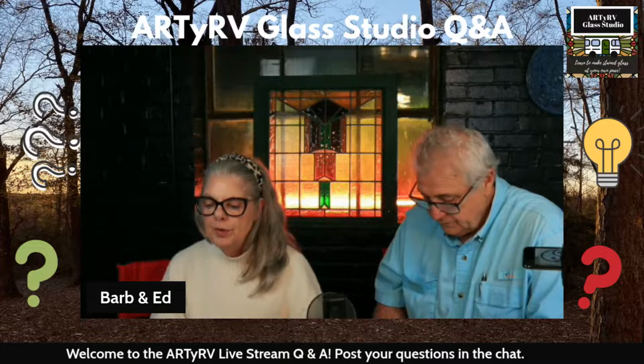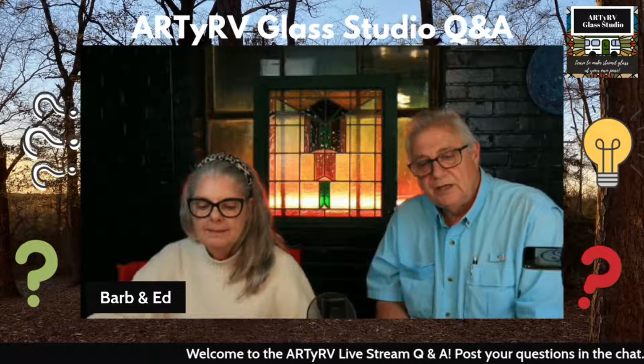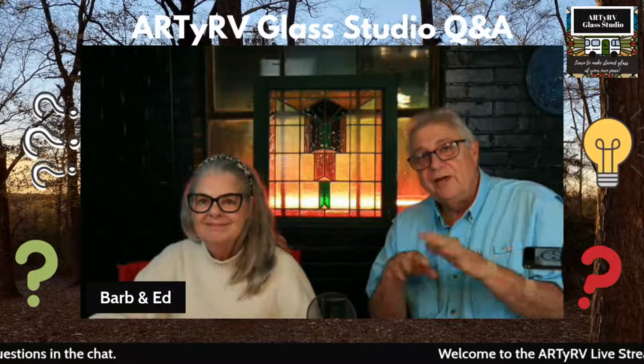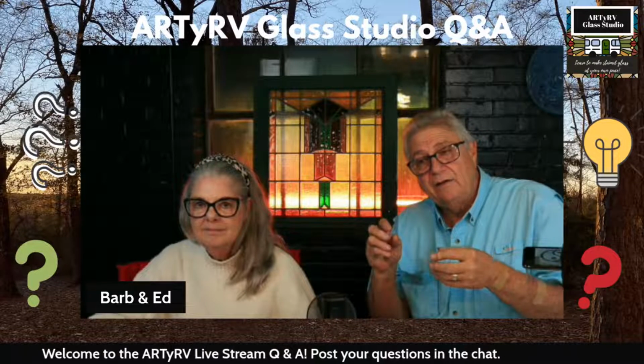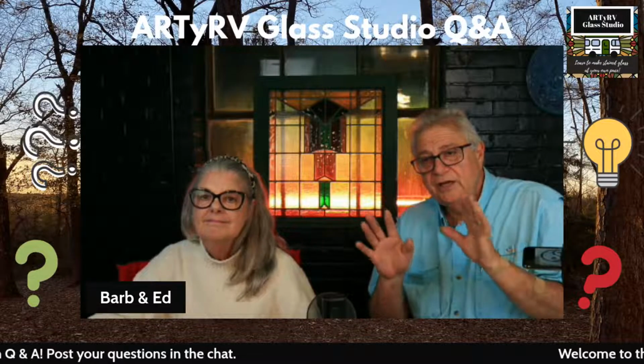Okay, Magali has a question. When fusing with her little kiln, will it affect the way the glass reacts if I use it in the garage since it's warmer, or is it better to use it inside? She's only doing jewelry. The humidity is not going to affect it, Magali. As long as you take it up slow, you're going to eliminate any moisture, whether it's in your house or in your garage. And of course, where you live, you have a lot of humidity. But if you take it up slow enough in the beginning, with the plug out, let it get up to 500, put the plug in and let it finish what it's doing. The humidity will be gone out of that kiln.